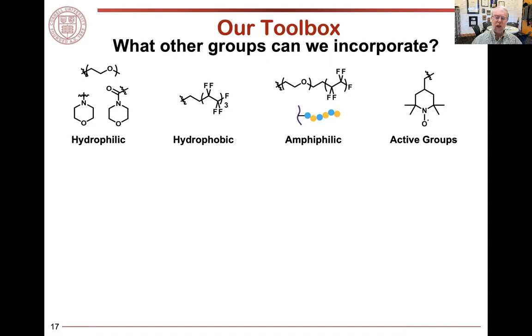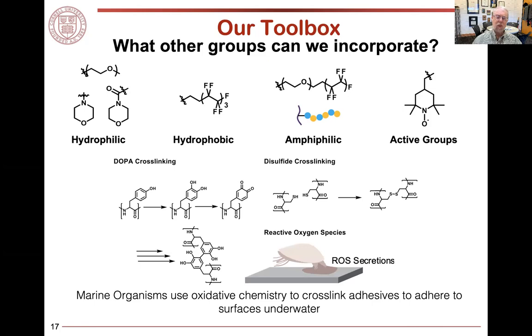But today what I want to do is talk about some active groups that we're introducing. And these are radical inhibitors. And the reason we're interested in them is because so many of the hard foulers cure their adhesives through an oxidation mechanism. Some oxidize DOPA, some oxidize disulfides. Other types of chemistry also can be cured. And so it's the cross-linking that makes the adhesive robust.